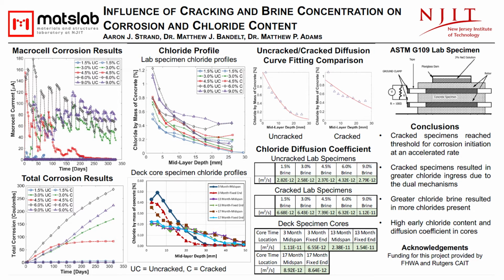Again, this is likely attributed to the higher crack width of the cracked specimen compared to the rest of the cracked specimens. At the reinforcement, the cracked specimens have noticeably higher chloride contents, with the chloride content of the cracked 1.5% brine found to be higher than that of the uncracked specimen ponded with the highest 9% brine. This highlights the importance of understanding the cracked system's rate of chloride ingress.